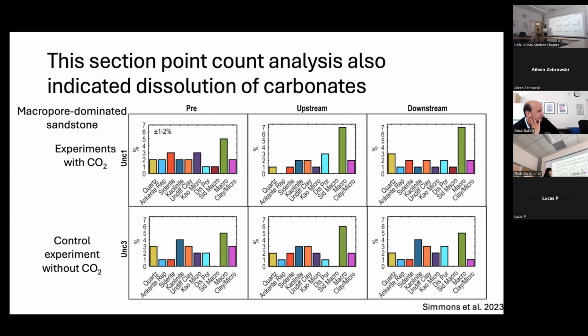These are the point counts of thin sections. If you're focusing on clay, kaolinite, siderite, and macropores, macro means the porosity, or the pore size, is big enough to be called macro. Pre-test and post: the green color bar all slightly increased after the experiment. So it means that there was some pore opening during the experiment. So, dissolution.